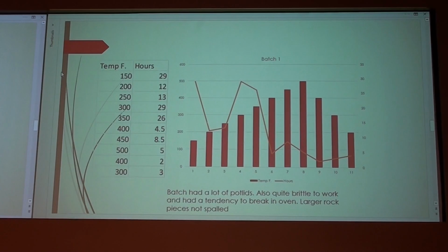And when I brought it back down at 300, I just basically shut off the heat and then let it naturally cool. It's in a sand matrix that I put it in so that the heat is more even, and when they do explode, they don't go all over the place. So they stay within a